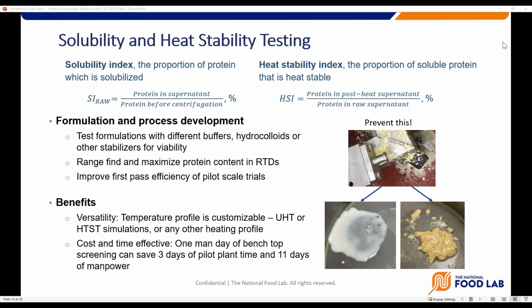You can quickly and efficiently test the viability of more complex formulations that include buffers, hydrocolloids, or other stabilizers alongside the proteins. As mentioned before, the method is flexible in terms of temperature and time exposure, and it's quite cost effective. 1 man-day of benchtop screening can save 3 days of pilot plant time and up to 11 days of manpower, which you'd need to interrupt your production and start cleaning the microthermics if you get in any kind of situations like the ones pictured here.